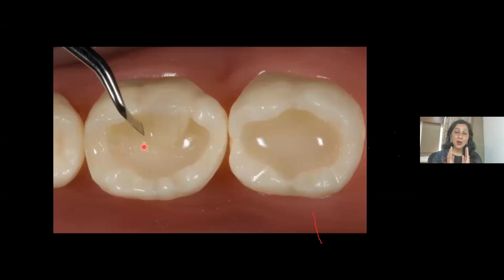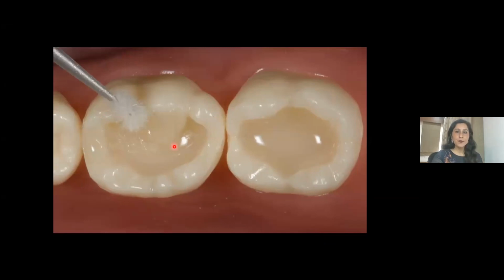So your light cure can also go to the buccal and the lingual area where you want your light curing material to be cured very well. And similarly, the light can go to all the surfaces of this tooth unhindered. So I like always converting my class 2s into a class 1, removing the matrix band and retainers, and then filling this class 1 with a vertical incremental technique.